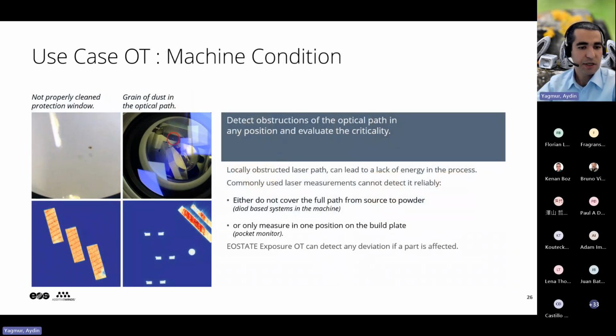Some examples, use cases. If there is dirt or problems on the optical path that affect the laser beam, we can detect them easily with OT because we see anomalies, which can also be automatically detected, always in the same position. This is a good indication that there is something wrong in the optical path, avoiding proper or optimized laser material interaction, and it should be solved.